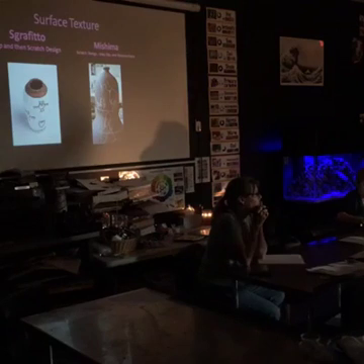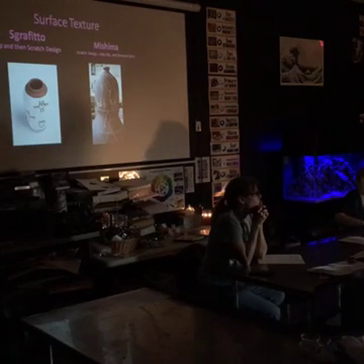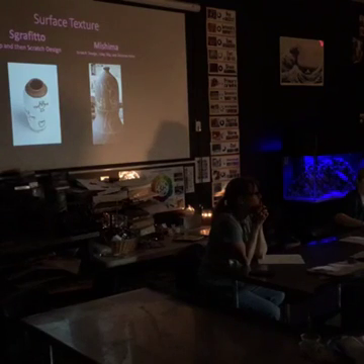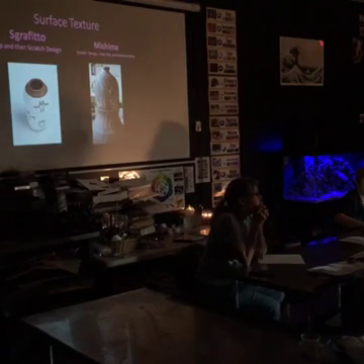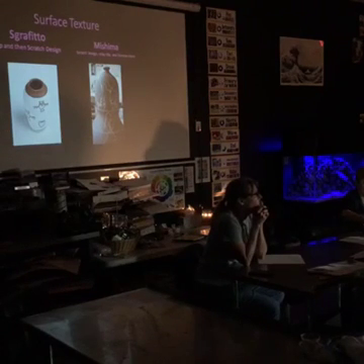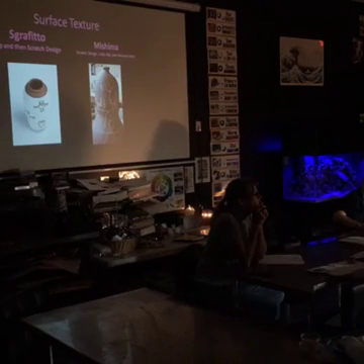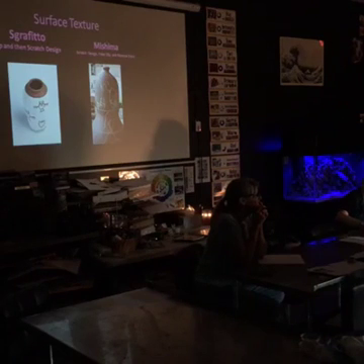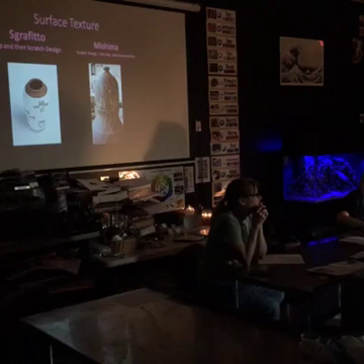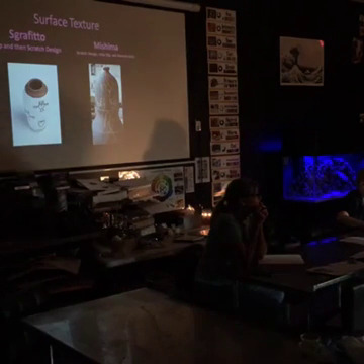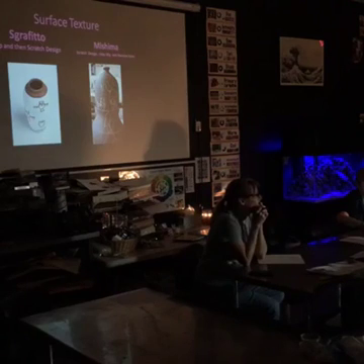You want to think about the height and width. The more horizontally you build with wet clay, the more it's going to want to sag. So remember, gravity is going to pull down anything that's out. Anything that's up is going to be stronger and easier, but if you really want to start a flare, all you have to do is let it dry a little bit, because as it gets more dry, it's stronger. So for instance, if I wanted to build this, instead of stopping, I would build a couple coils, let it dry for 30 minutes or an hour, then build more, just be a little bit more gradual. I would have high school kids that got super excited, but you have to be a little patient if you have horizontals, okay?